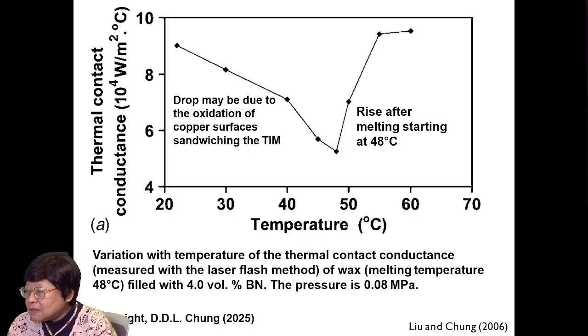Here shows the thermal contact conductance versus temperature for the wax as the PCM filled with 4% boron nitride. And you can see the thermal contact conductance drop as you heat, and then further heating causes the conductance to rise. The drop may be due to the oxidation of the copper surfaces sandwiching the TIM. The rise afterward occurs after the start of the melting at 48 degrees C for this wax.